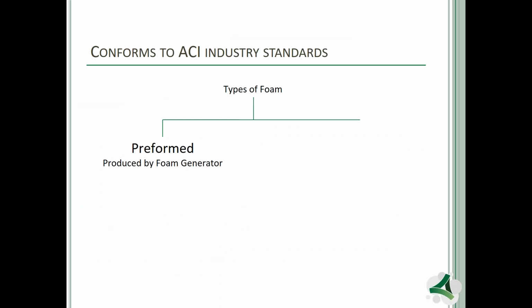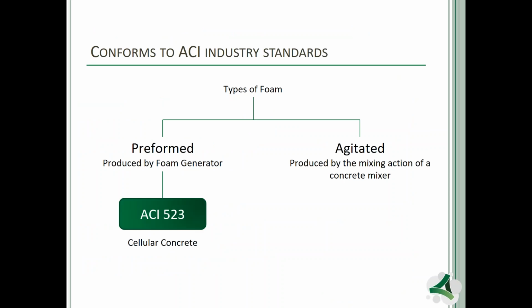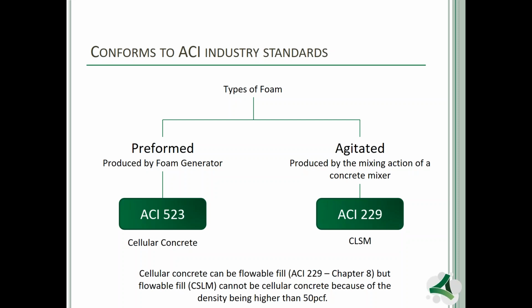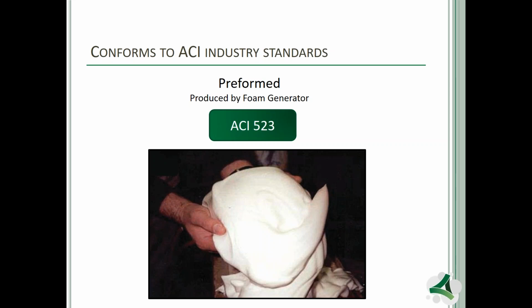Under the ASTM standards, we're looking at two types of foaming agents. We've got the preformed foam, and then we have the agitated foam, which you're probably more familiar with because that is the flowable fill under ACI 229. Now, I'll confuse the issue a little bit more here, because a cellular concrete can be a flowable fill, but a flowable fill cannot be a cellular concrete, and that is purely by definition, because again, the preformed foam is under 50 pounds per cubic foot. So I'll repeat that one more time. A cellular concrete can be a flowable fill, but a flowable fill cannot be a cellular concrete. And again, that's purely by definition. Today, I'm going to spend most of the 45 minutes here on the ACI 523, which is under 50 pounds per cubic foot.